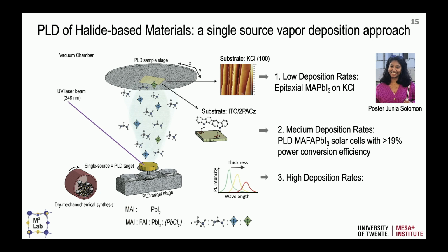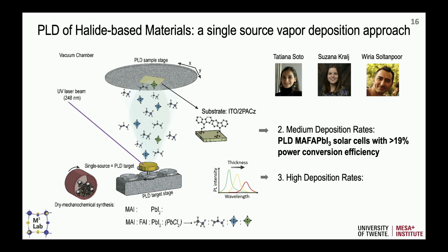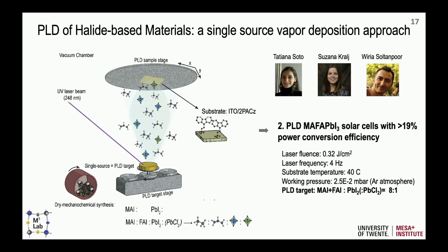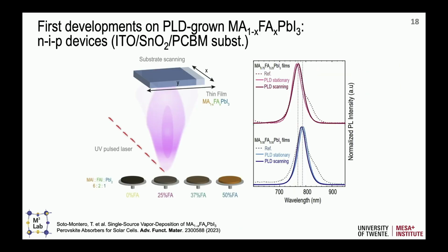The other one is about how we go for making actually solar cells. So the other motivation, of course, is can we make devices with this? And this is the work of Tatiana Soto here, Susana, and also Wiria, that was a postdoc in my group. And here we actually work with methylammonium formamidinium lead iodide, because we can work with MAPI, but mixing MA and FA, it was, first of all, one challenge more, because we want to prove we can do the two molecules, but also we can stabilize the cubic phase on polycrystalline films, which is something that was actually known.